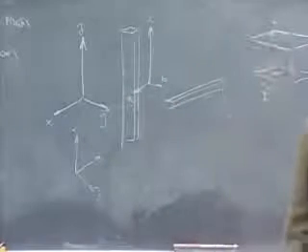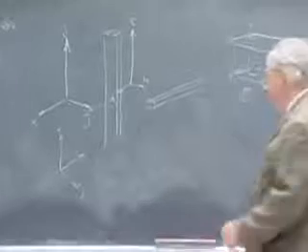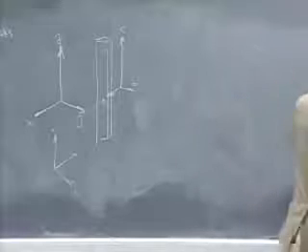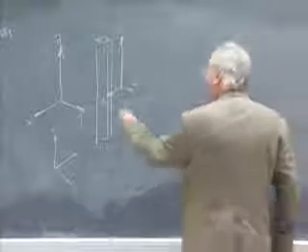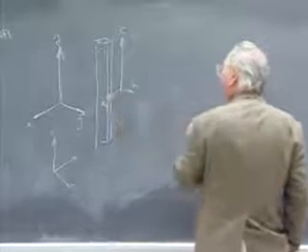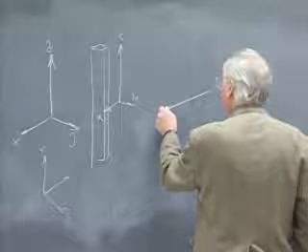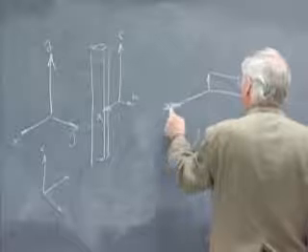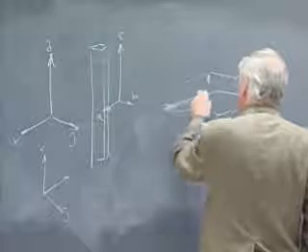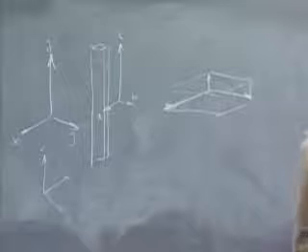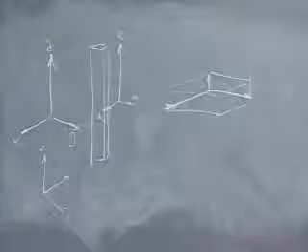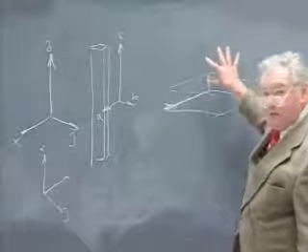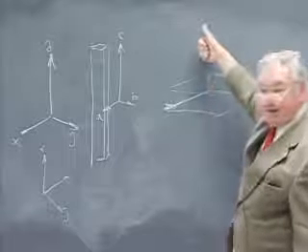And there were tons of pages published with drawings of crystal morphology on them. And then along came X-rays, and when they began to determine lattice constants of a material that looked like this, almost invariably they found the translations inside of a needle-like crystal corresponded to a unit cell in the shape of a pancake. Crystals, when they have a very, very short lattice vector, almost always grow most rapidly in that direction.